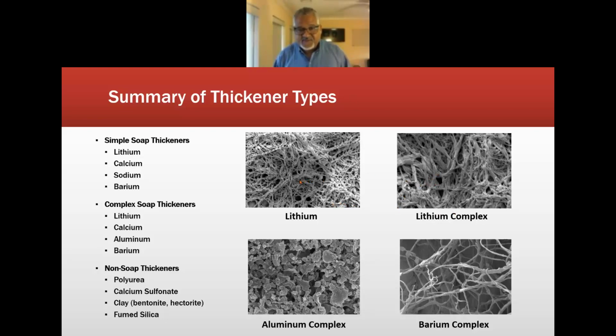So you have a lithium with smaller fibers and lithium complex with thicker fibers that hold on to the base oil a lot easier. Aluminum complex grease, I gotta be straight up, I've never been a fan of aluminum complex greases. We all make them, use them for possible wet applications or food grade applications, but they don't tend to hold on to base oils as well as the lithium complex or the calcium sulfonates. And the barium complex is the strongest thickener and has the strongest fibers. The thickeners that hold up to shear the best.